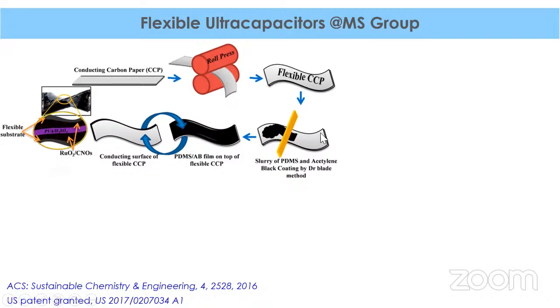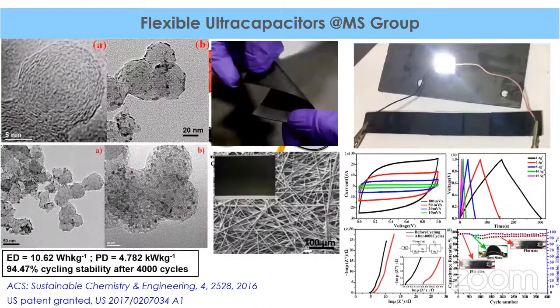Then it was dried and cured, and a polymer gel electrolyte comprising polyvinyl alcohol along with 1 molar H2SO4 was prepared and coated on the other side. Then he coated the active electrode material. Here he used a composite of carbon nano-onions, or multilayer fullerenes, and ruthenium oxide. Two such electrodes are brought together with the gel electrolyte sandwiched between them, and he made such a device.